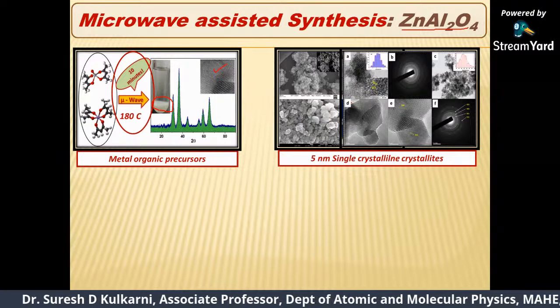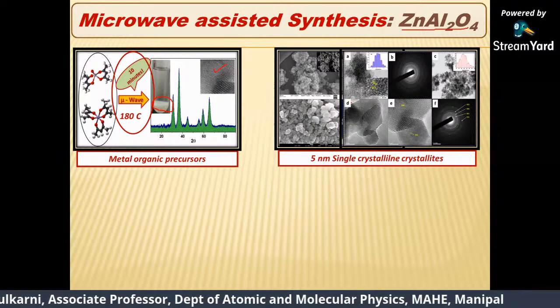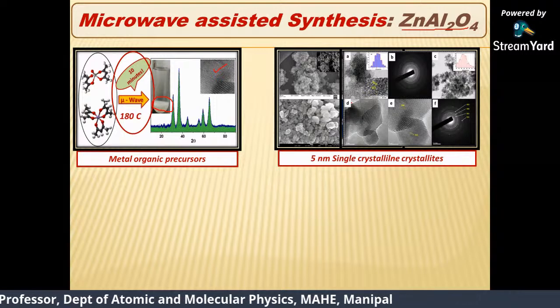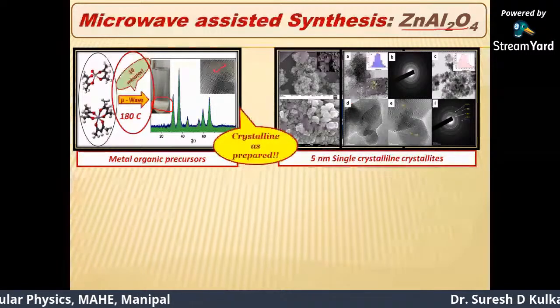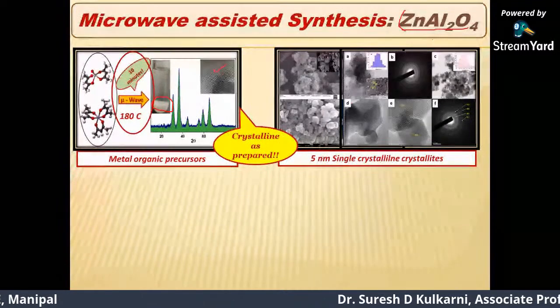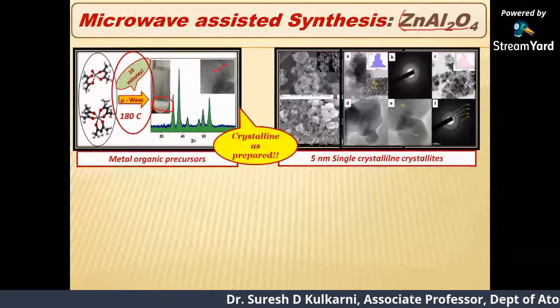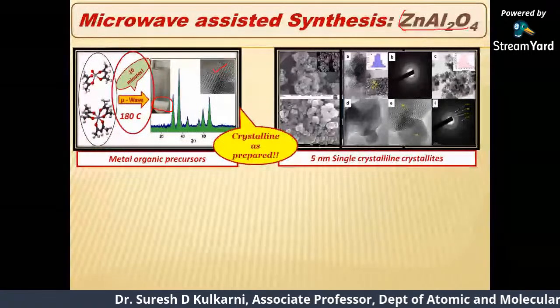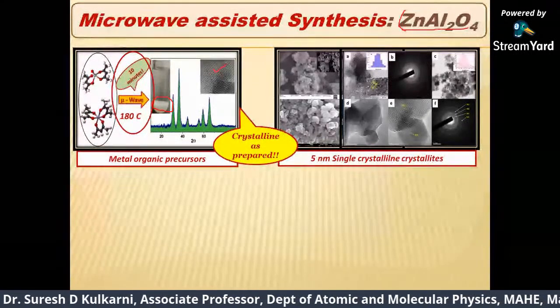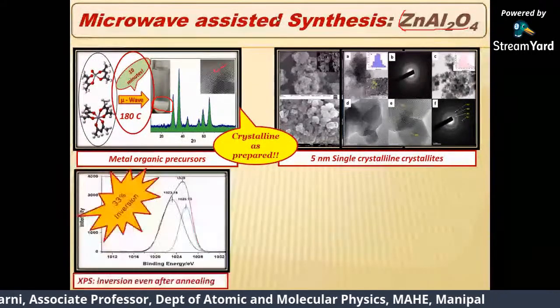Crystalline material at 180 degrees in just 10 minutes. That's a significant achievement, especially considering a ceramic like zinc aluminate. These are refractory oxides generally synthesized at high temperatures, but we are able to synthesize the material in quick time, and that too at a lower temperature.